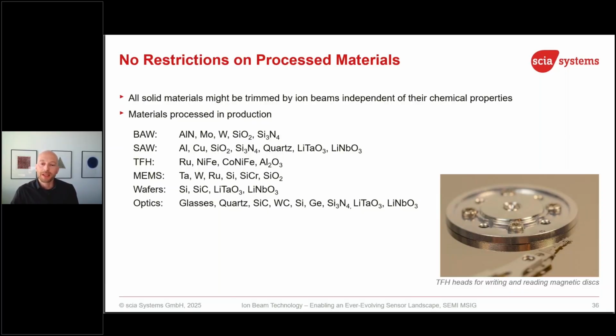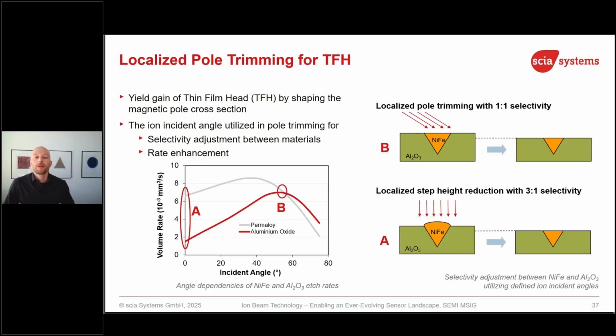So how could ion beam trimming help to make read-write heads for hard disks? On a wafer where you make those heads for hard disks, there are thousands of those devices, of course. And the write pole is basically some magnetic material. The size is just a few 10 nanometers, defining the write track here, and there is a surrounding alumina matrix. And actually this is done by CMP. You CMP your wafer, and then you get that kind of shape. Unfortunately, CMP is not perfect. So on some areas on the wafer, you might see that this is still too thick, meaning the write pole is too wide, it's not small enough. On other areas on the wafer, it's already small enough. So we can use ion beam trimming in order to locally etch some material away on a 200 millimeter wafer to have all the write poles at the same thickness.